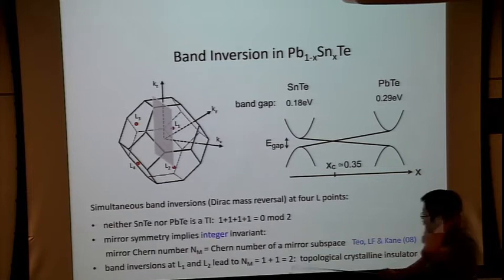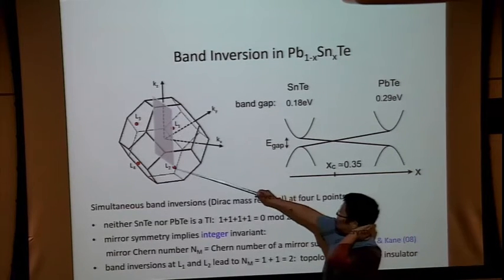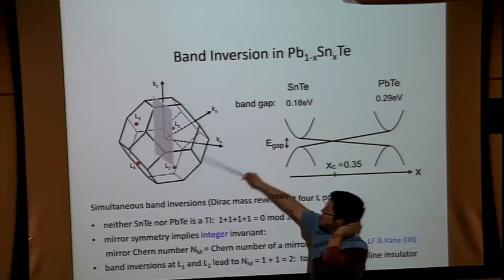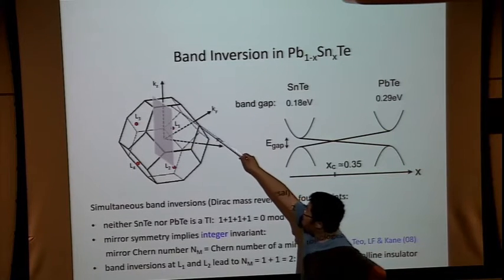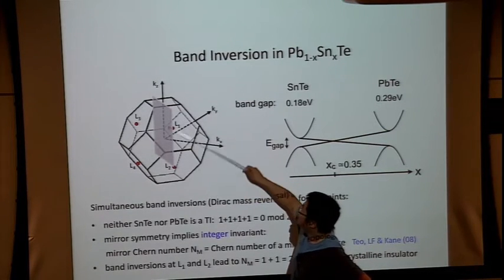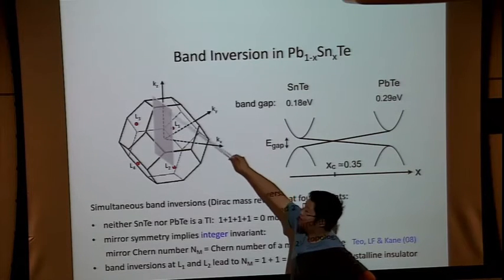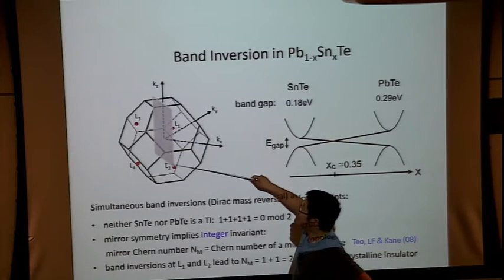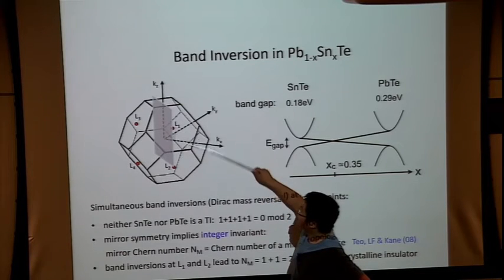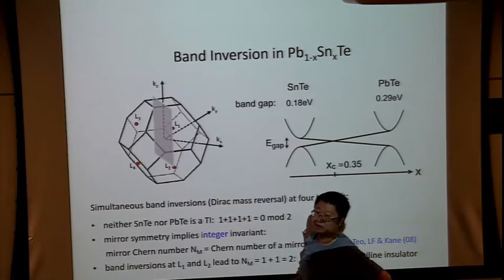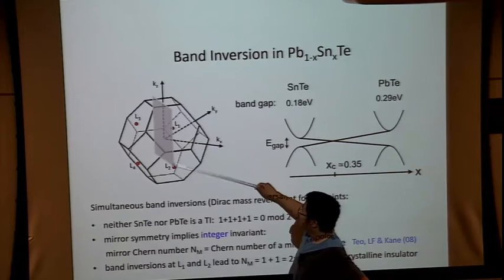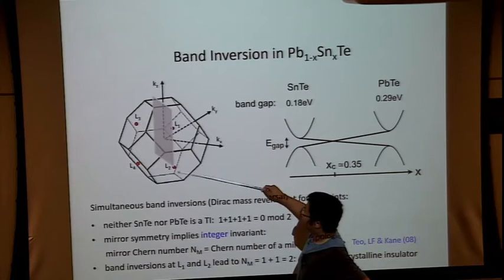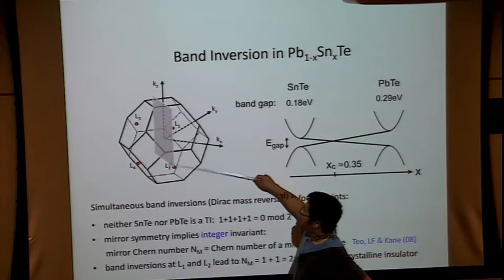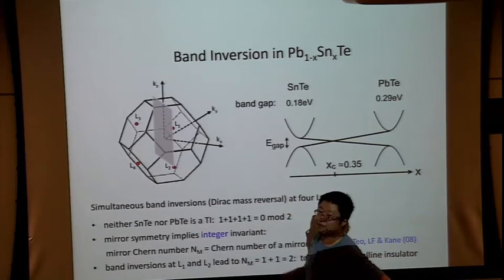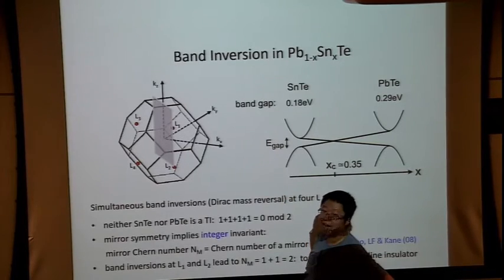One can further show that the band inversion at all these, for example, if I look at a particular reflection symmetry x to minus x, then there's this particular plane that is invariant under this reflection, for which I can define the mirror Chern number. There are two L points falling onto this plane. As band inversion occurs, the mirror Chern number changes by 1 at the L1 point and by 1 at the L2 point. The changes of the Chern number at L1 and L2 are identical.